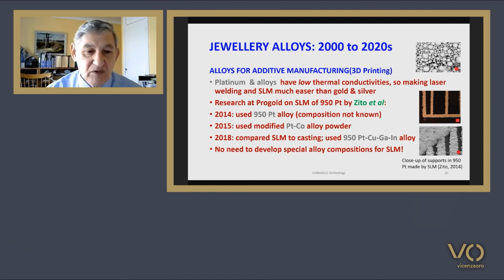than gold and silver. There's particularly been a lot of research at Progold on the selective laser melting of 950 platinum alloys by Damiano Zito and his co-workers. In a study they reported in 2014, they used a 950 platinum alloy but didn't give details of its composition. In 2015, they used an alloy which they said was a modified platinum cobalt alloy, a little bit different to the alloy they used in their 2014 study.